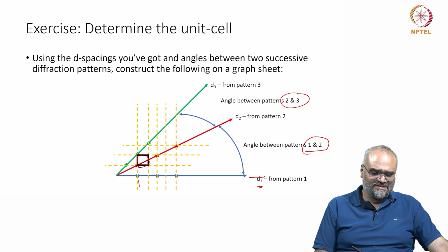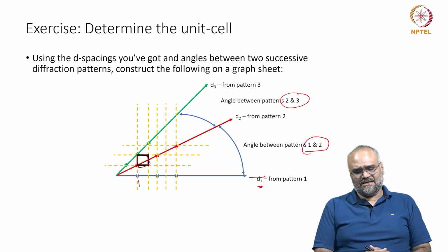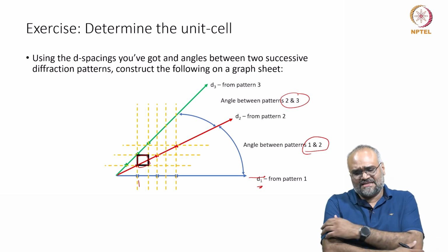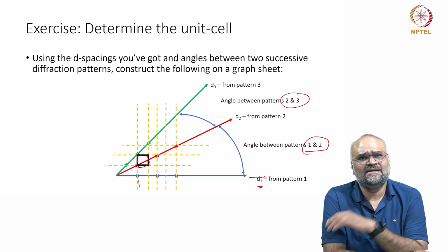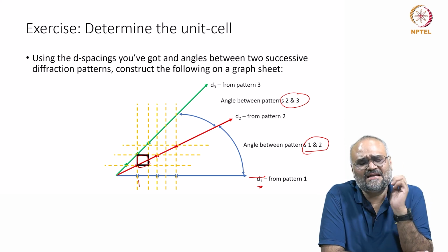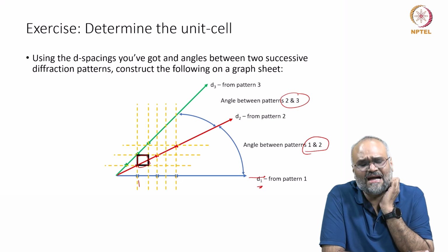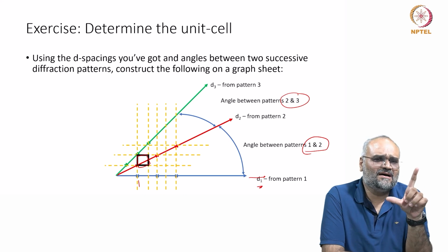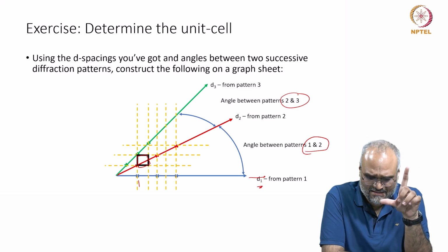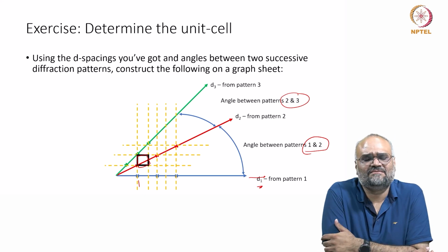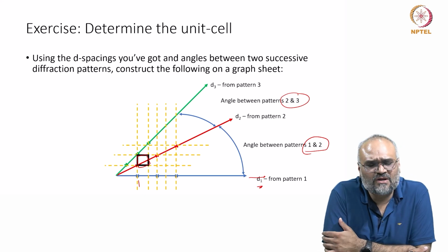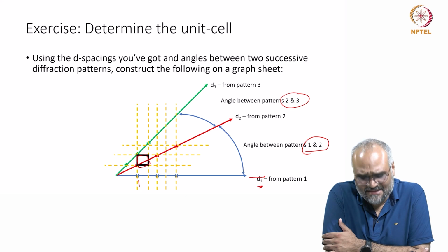What you can do is to actually get a better accuracy, and please remember that there will always be some experimental errors in orienting the crystal exactly into the zone axis. There is a high likelihood that the spacings you see may not actually have orthogonal angles between the unit cell projections that you see here, if you are expecting an orthogonal Bravais lattice.